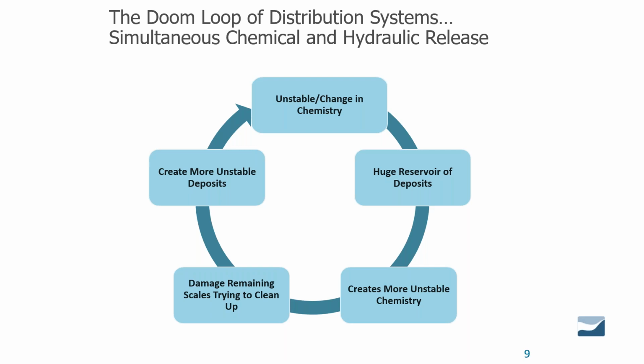And then we run out, we start opening hydrants, we start moving water, flushing, breaking off tubercles, and we damage the scales while we're trying to clean up. That exposes new fresh surfaces to have further reactions with the chemistry, and you can just see you truly can get into a doom loop. And it's this exact process that we are trying to avoid.